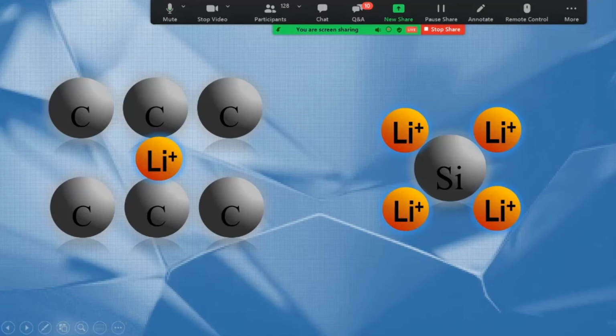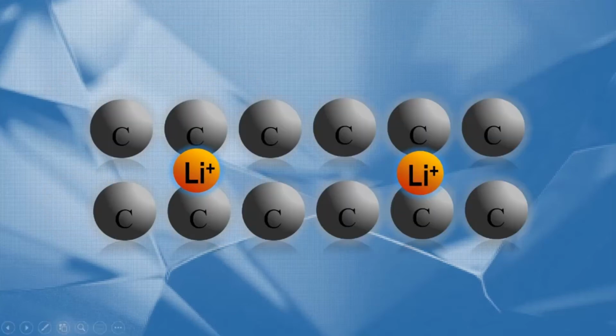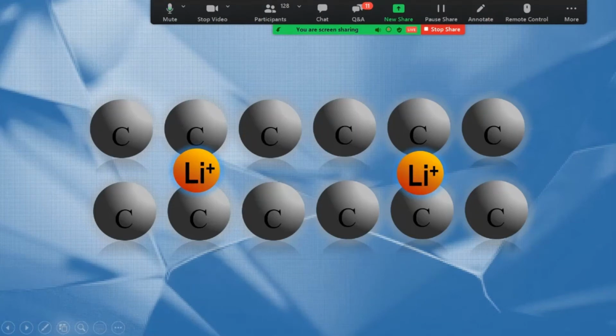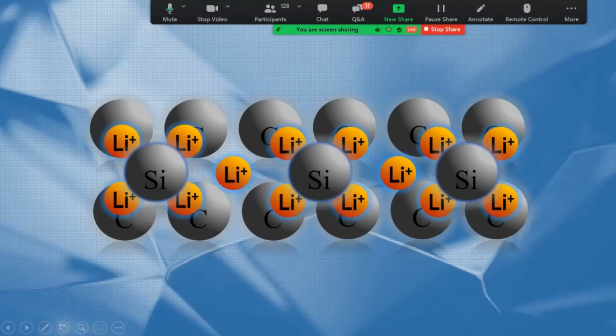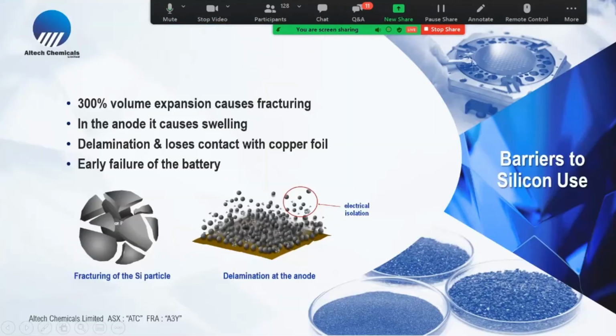Now, just to give you an idea of the capacity of silicon to hold lithium, on the left-hand side, you need 6 carbon atoms to hold 1 lithium ion. On the right-hand side, it shows that you only need 1 silicon atom to hold 4 lithium ions. Now, if this was the anode material of a graphite battery, if you can put some silicon particles in there, this is how much lithium that battery can hold. So you can see visually that the energy density of the batteries increases significantly by adding silicon into the batteries.